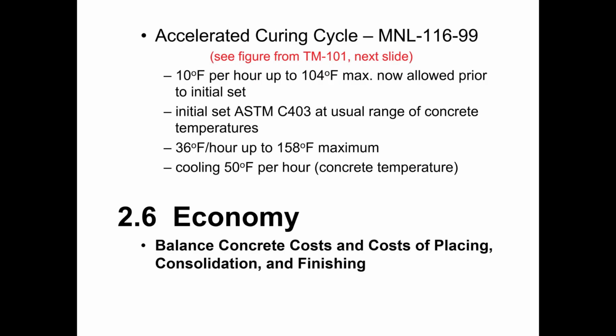It is determined by ASTM C403 by separating out the coarse aggregate from a sample of your mix design and then using a penetrometer over a period of time to determine when that mortar sample reaches a strength of 500 psi. Once we've reached initial set, we can heat the concrete up a maximum of 36 degrees per hour up to a maximum of 158 degrees.